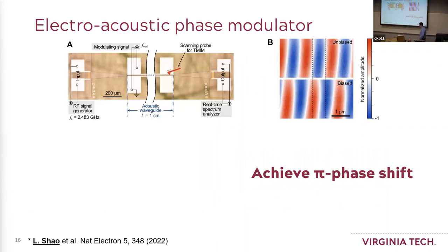The first thing we demonstrate using this electroacoustic modulation concept is phase modulation. What we want to do here is make an acoustic waveguide, put the electrodes down, and apply voltage. Then we can control the phase of the acoustic wave at the output. This is a device, and this scan was actually helped by my collaborator at UT Austin, Professor Kurtz. While we don't have any electric field applied on this electrode, we get the phase scan of the acoustic wave, shown in the upper figure. But if we apply an electric field, we can see the phase gets totally shifted. So it can have the phase change.